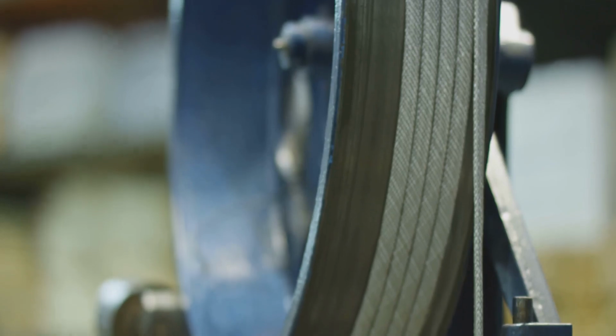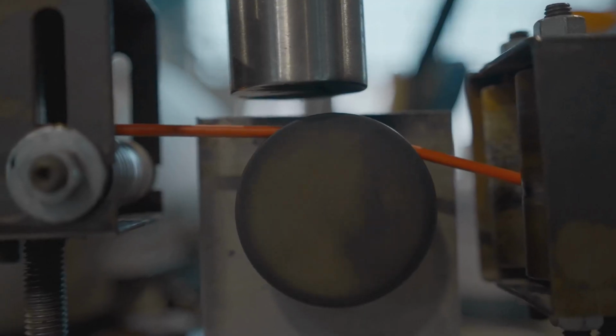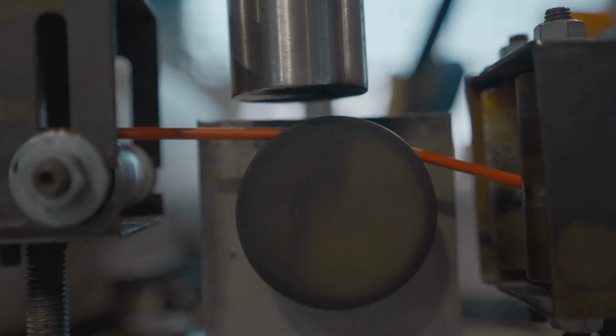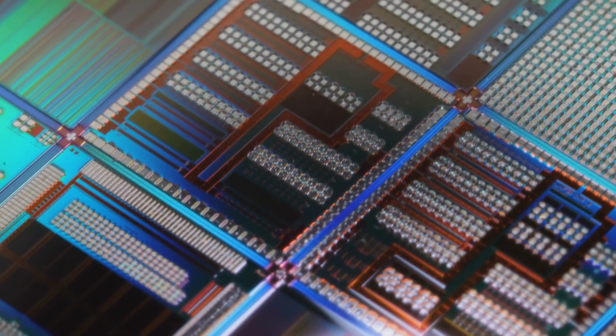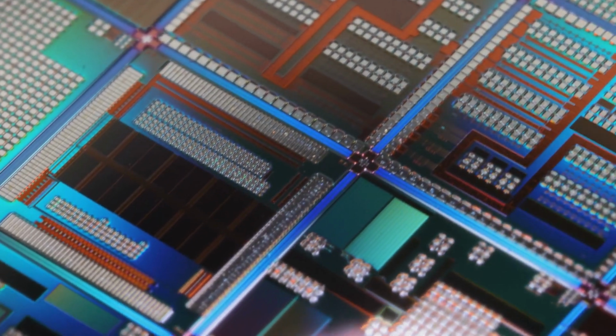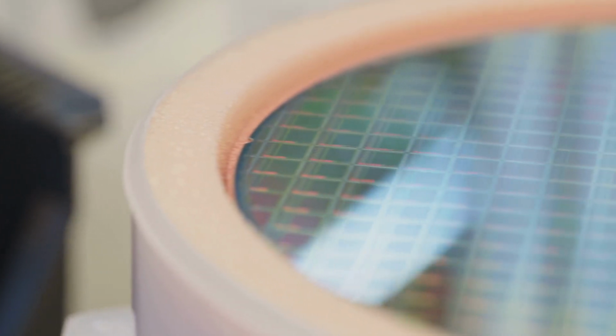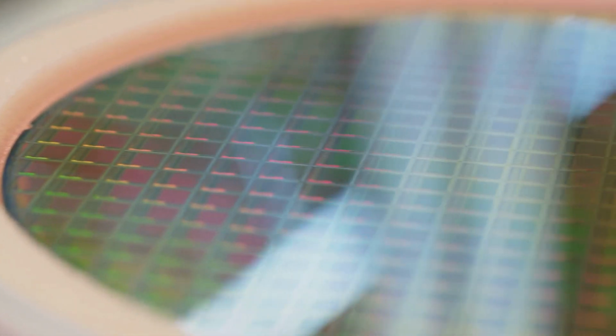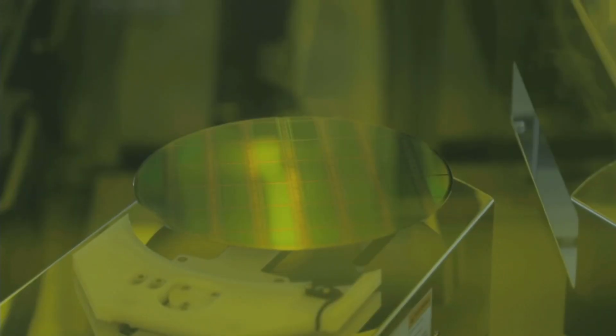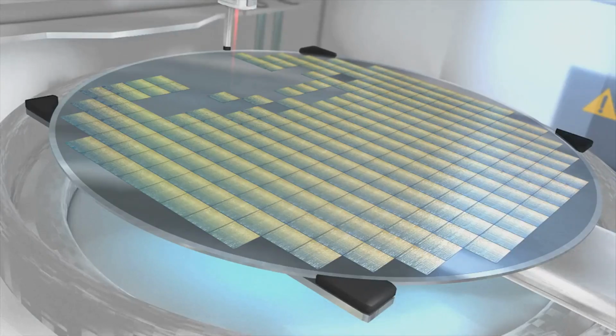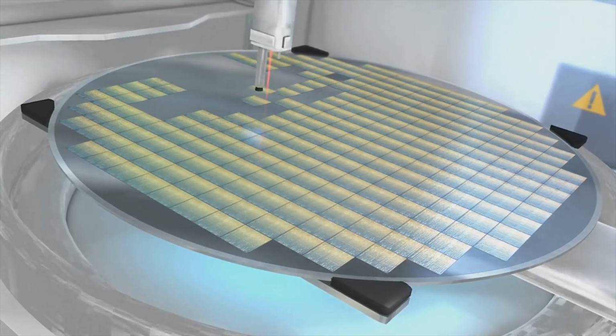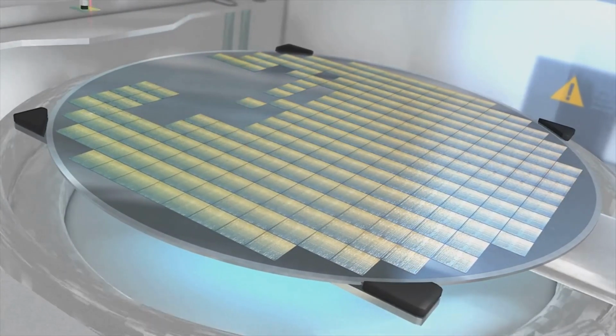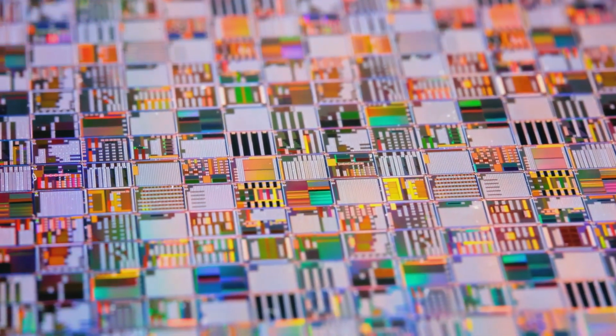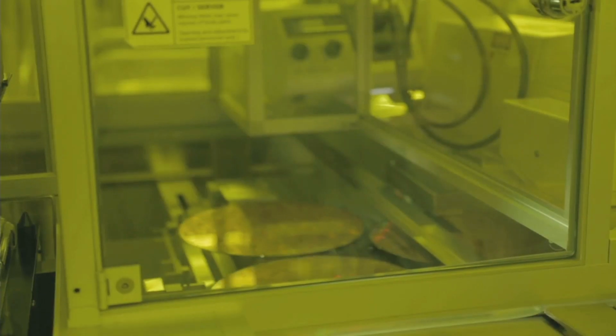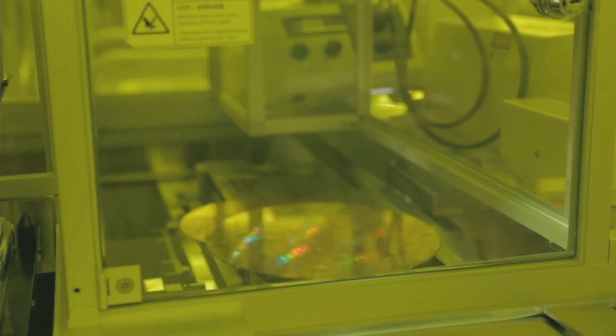These wires, often thinner than a human hair, are coated with abrasive particles like silicon carbide. Multiple wires move back and forth across the ingot. They slowly, carefully cut through the hard silicon. The wafers produced are astonishingly thin. Typically, they are around 160 to 180 micrometers thick. From a single ingot, thousands of these delicate wafers can be cut. Each one must be almost perfectly flat and uniform in thickness.